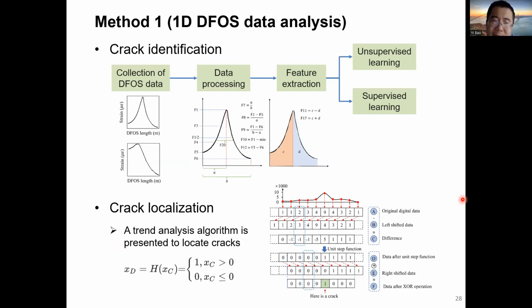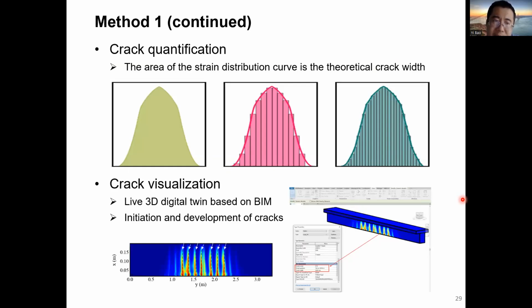So we developed two main methods for the data analysis. The first method is a relatively simple method based on peak detection. Because when we have a crack, we will generate a peak in the strain distribution, and we propose to integrate the peak detection and some other technologies to achieve crack detection, quantification, and visualization. So based on the machine learning results, we could analyze and understand the sensor data automatically, and this processed data could be used to generate a 3D digital twin model for the structure. And this model was related to our distributed sensor system. So this digital twin is a live digital twin that can update in real time.